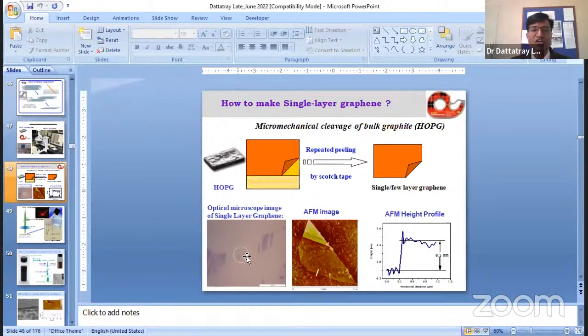These are some color contrasts by which you can identify whether the graphene transferred on the SiO2 is 1-layer or 2-layer material. Of course, you can do AFM, atomic force microscopy, or scanning probe microscopy, TEM. But the most accurate measurement for thickness or layer identification is Raman spectroscopy. I will tell you in a couple of minutes.